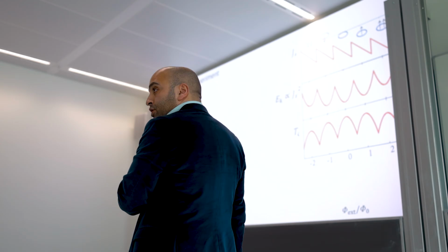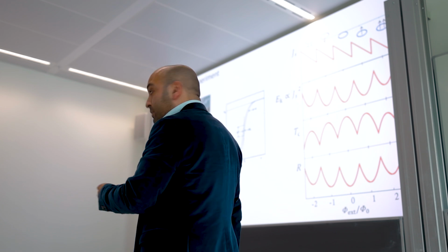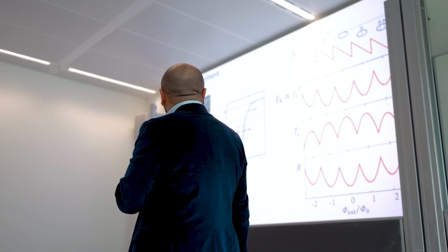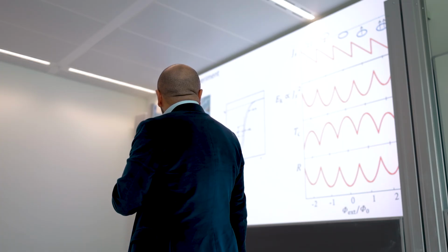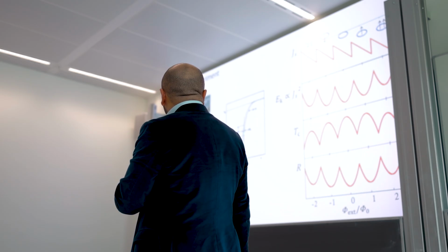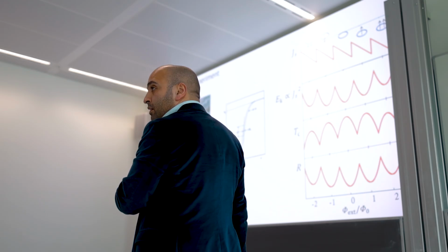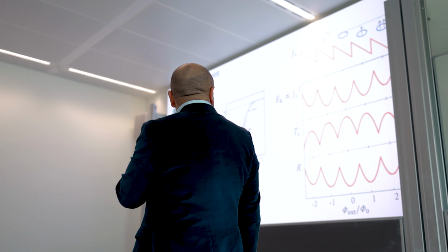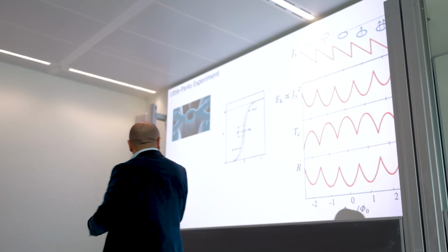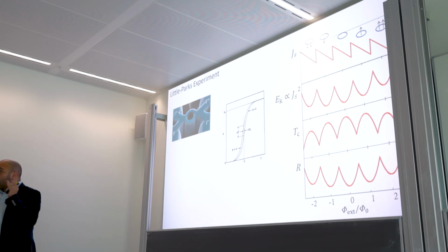Well, you want to measure Tc, you need to be at the transition. So what you look at is the resistance measurement. So you do a magnetoresistance measurement, and the way to do it is that if this is your transition curve, of course, there's a bit of a period before the superconductor goes from normal to superconducting. So you park your temperature right here, and now if the transition temperature goes down, suddenly your resistance goes up, and as the transition temperature goes back up again, resistance goes down. So it ends up looking exactly like what your kinetic energy looked like. So these are called Little-Parks oscillations, and they're still relevant to this day.